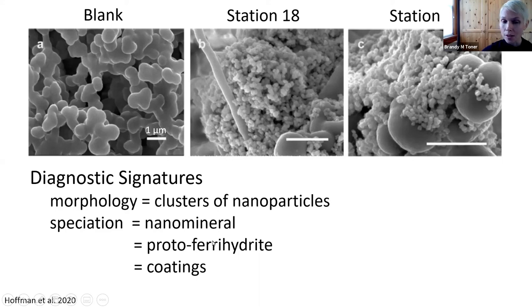So we have clusters of nanoparticles from a morphological point of view. The iron speciation, you know, it's hard. We don't have a specific name for it. We could call it a short-range ordered material. We could call it, my postdoc advisor used to really favor this, the idea of a proto-ferrihydrite. This is a material that would have formed ferrihydrite if it hadn't gotten gummed up with organic materials or some other process that capped reactive sites. So we think of the chemical speciation of the particulate iron as being a nanomineral, something that looked like it was going to become a ferrihydrite, but because of coatings, perhaps did not make it.